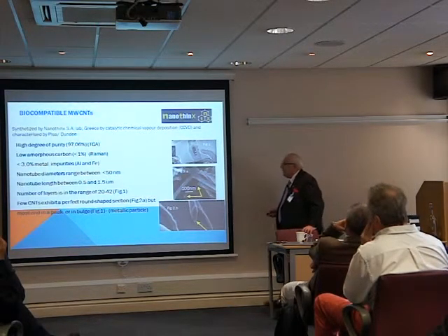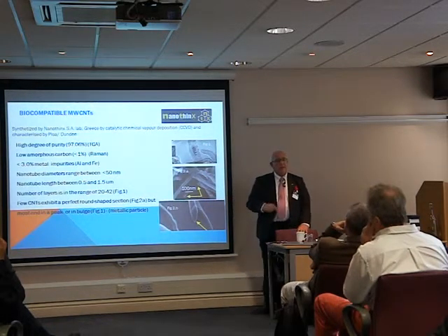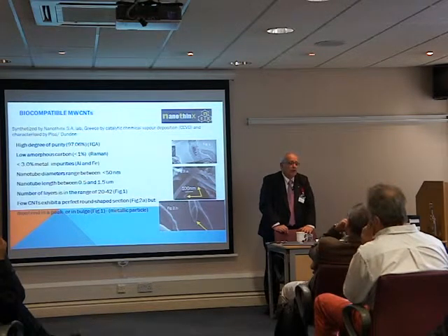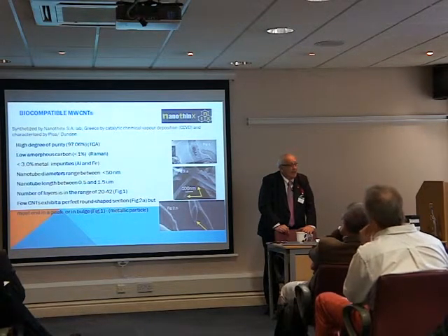The length is very important. In my opinion, for biomedical application, no carbon nanotube should be longer than 1.5 micron. Whereas experiments show you that if you have long carbon nanotubes, certainly greater than 10 microns, they behave like asbestos fibers.